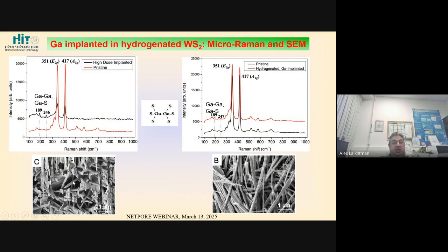First of all, you can see that indeed when you use a high ion dose, let's say in the range of 10^16, 10^17 per square centimeter, we have a change in the structure, a kind of melting of nanotubes, so not something that we wanted to proceed with. In the case of the dose of 10^15, the structure is preserved.